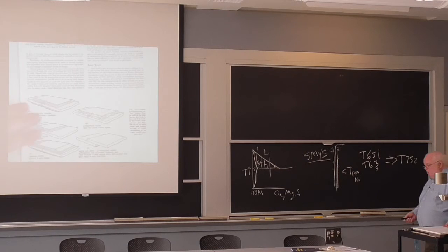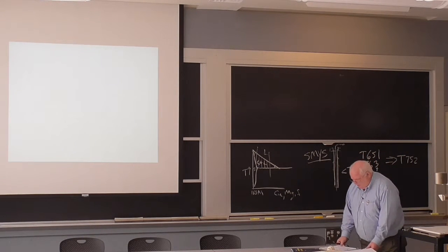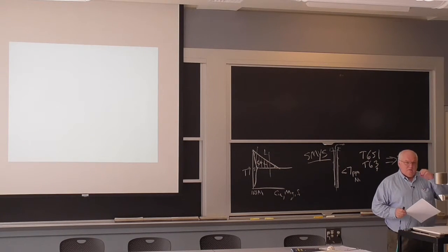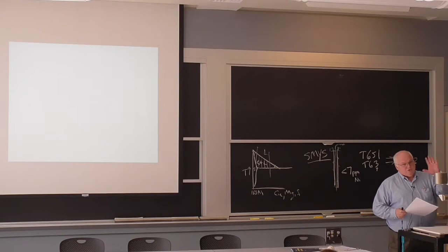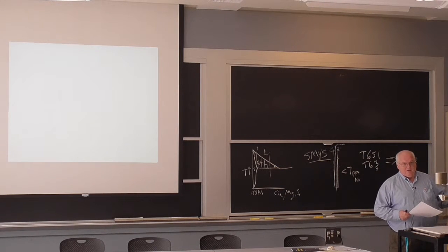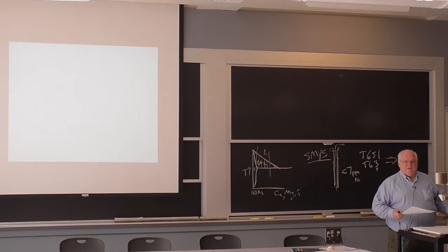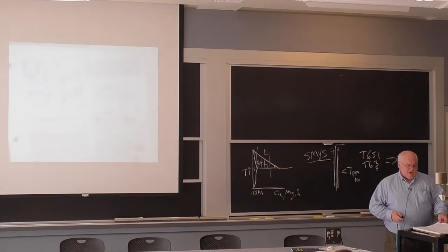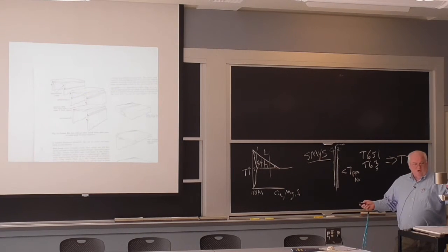Let's talk a little bit about aluminum. One of the problems with heat treated aluminum, I told you yesterday, non-heat treated aluminum, like the 5000 series, we just use alloying elements to strengthen it. And then you're only going to get 20 or 25 KSI, which is less than the strength of steel, but it's a lot lighter. So the overall strength to weight ratio is better for aluminum. You can make light weight ships out of non-heat treated aluminum alloys. Well, if you go to heat treated alloys, because you have to go through this precipitation, solutionizing and precipitation and heat treatment and tempering, just like you get the highest strength steels, you can't match that in the weld metal with aluminum. You can with steels. We can weld HY80 or HY100, which has been heat treated, and we actually have weld metals that can give us, match the strength, even though they're a cast structure. I don't want to get into all the metallurgy why. But we can match the strength in steel weld metal all the way up to a couple hundred KSI. Aluminum, you can't do that. It doesn't have the same properties of transforming crystal structure from FCC to BCC and stuff. Aluminum only has one crystal structure, FCC, through all the temperature range. So it turns out if you've got to weld heat treated aluminum alloy, you're going to have to play some games about getting more weld metal in that groove than you can fit in the groove.